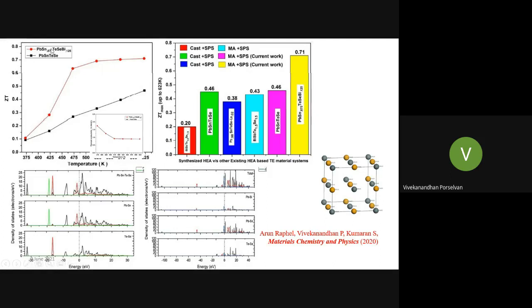And these are other examples, the PbSnTe alloy and the TeSb alloy, which show a unique variation in the density of states due to the bismuth doping at a concentration of 0.125. So here the high entropy phenomena reduce the thermal conductivity. At the same time, the bismuth doping in this particular high entropy semiconductor drastically changes the density of states, which is contributed by Pb, Sn and Te, Se. Thereby we can also have good electrical conductivity, and achieve a superior thermal conductivity of 0.71.